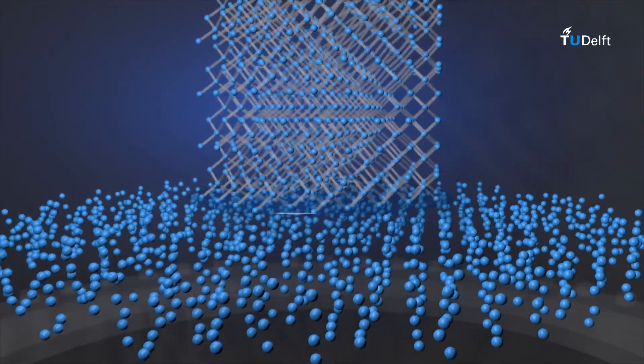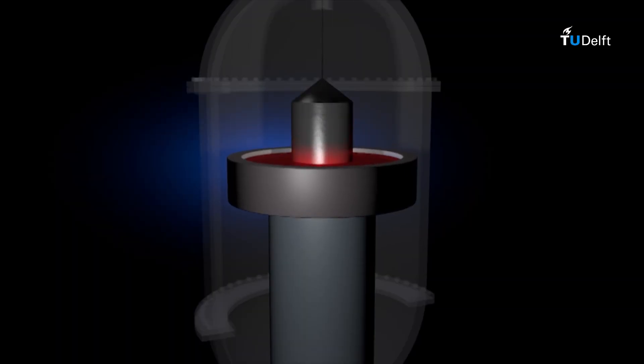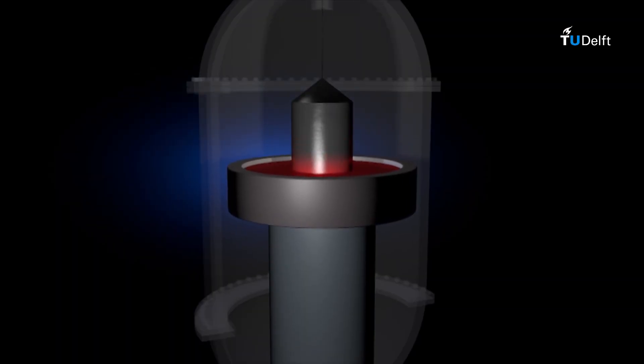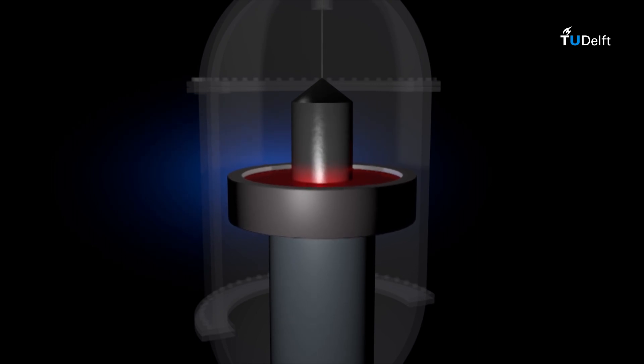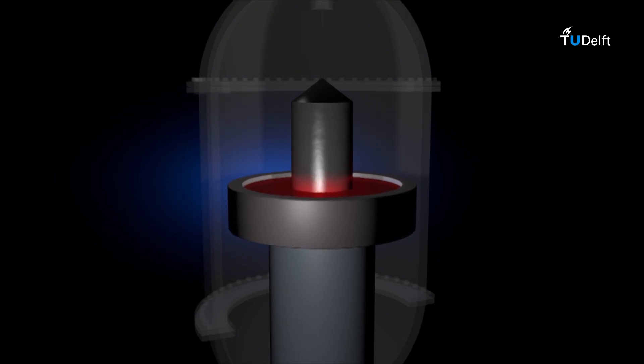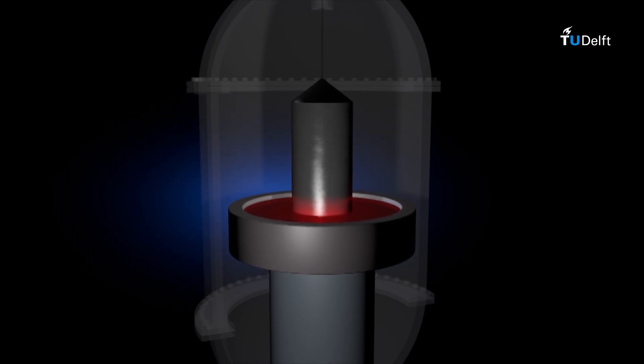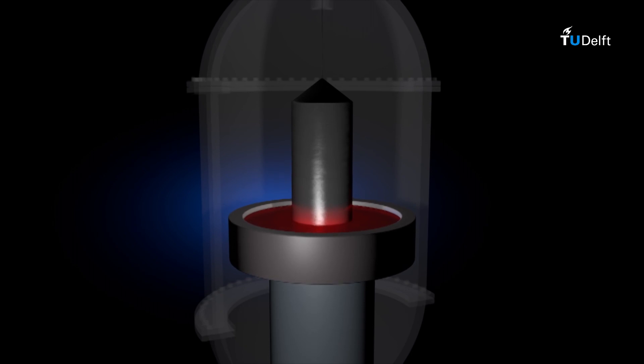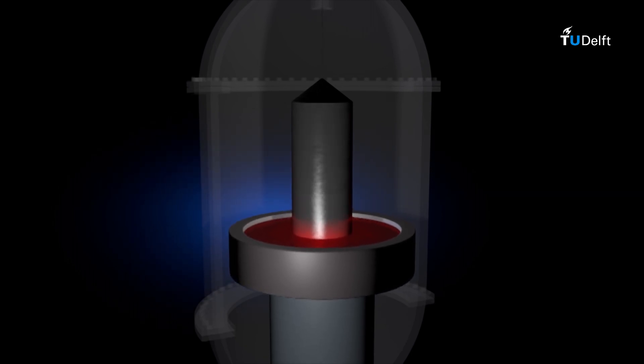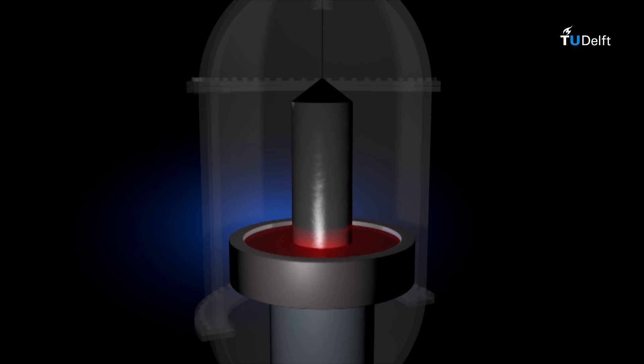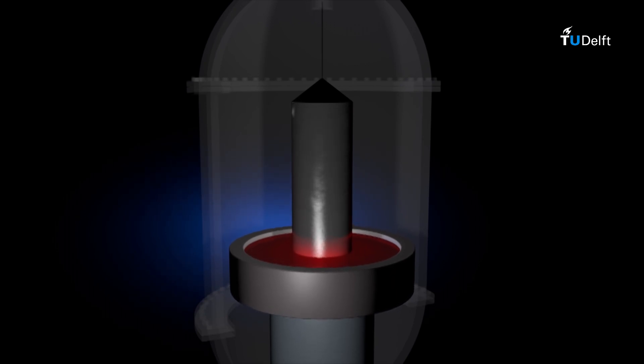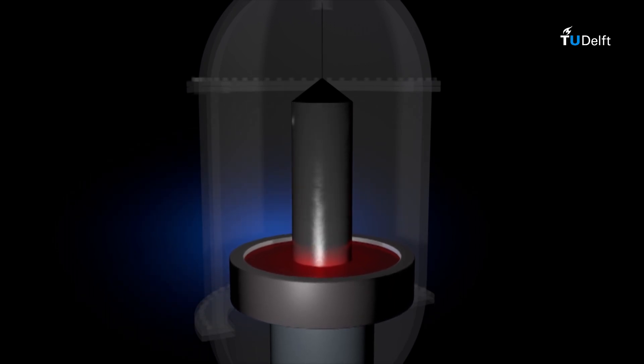In this process, the temperature gradients, rate of pulling up, and speed of rotation are precisely controlled. Nowadays, crystal ingots of diameters of 200 mm and 300 mm with lengths of 2 meters can be processed. To prevent the incorporation of impurities, this process takes place in an inert atmosphere such as argon gas.